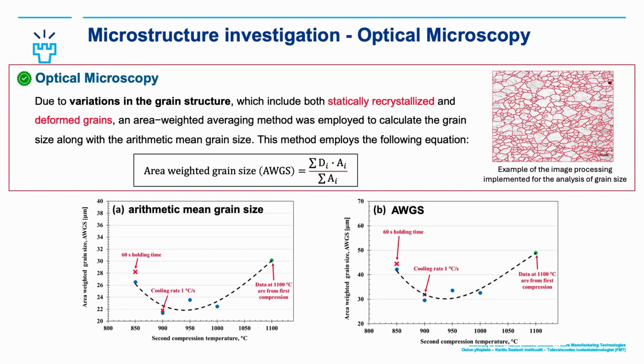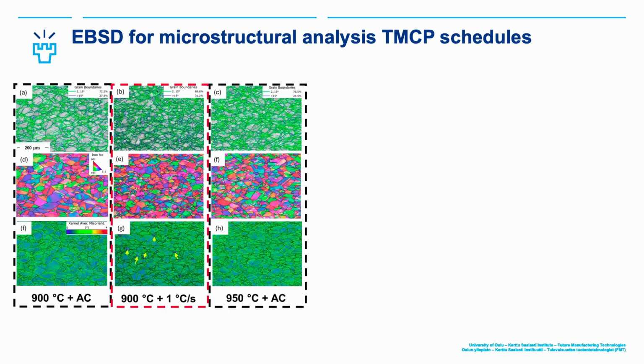But for all schedules, the grain size was much lower than the initial condition, which is the A condition I mentioned in the beginning. Moving to the EBSD, we have selected specimens for 900 air-cooled, 900 slow cooling or controlled cooling of 1 degree Celsius, and 950 with air cooling. The only thing to mention here is that there are strain-free grains with this slow cooling.